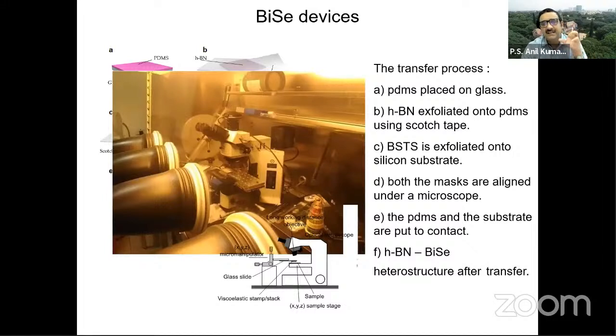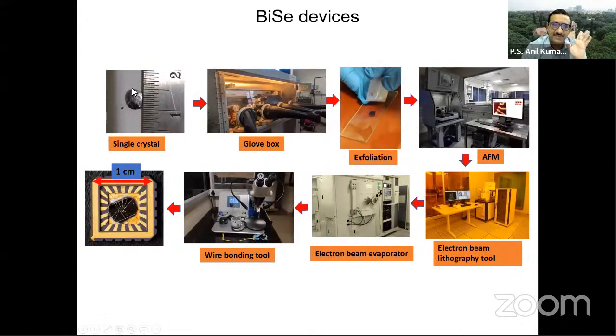This is all done, including the exfoliation and the device fabrication, in a glove box with extremely good conditions so that the moisture and oxygen are brought to a minimum level. Once we have these devices made, we have this process. We have the single crystal, exfoliate it, and then do AFM to find out the thicknesses, etc. Then we do the electron beam lithography, then the metallization of contacts, etc. Then you get it into the chip carrier and do the wire bonding. So this is the device that will go into the cryostat for the electrical transport studies.